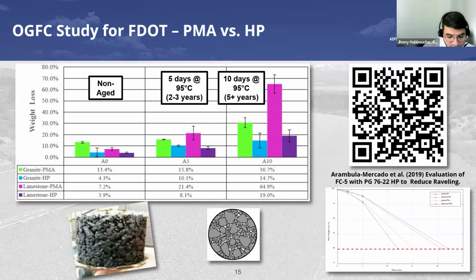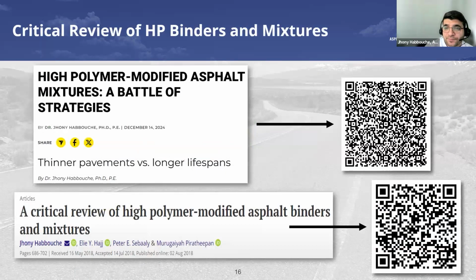Also, Florida showed interest in potentially doing a binder swap for their open graded friction course mixtures. They noticed that with a binder swap between PMA and HP, they can get about 7 to 8 years extension in the performance life of these types of mixes. And again, QR codes, if you're interested in the details of these studies, you can just scan these QR codes and get the reports, download them, and read them.